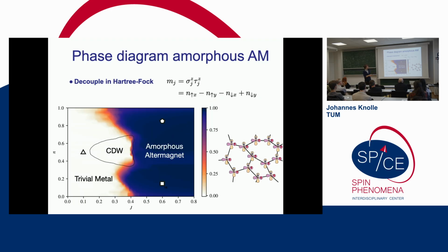Good, and so then you can again do Hartree-Fock, which now becomes a bit more technical because you can't use translation invariance, so it's a bit of a beast. But the nice thing is you really find that you get spontaneous symmetry breaking for a large regime where the orbitals choose spontaneously a direction that fixes your nodal planes, and the direction of the moment is also chosen spontaneously and so on. Okay.